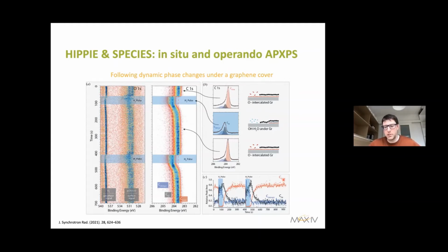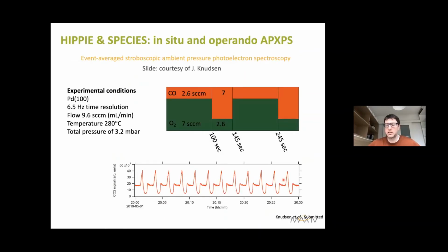In this particular case, the time resolution is on several tens of seconds. If you want to study faster processes, we need to slightly modify the method and choose a faster process. That was done in the next experiments, where a CO oxidation reaction on the transition metal palladium was studied. This oxidation is a pretty fast reaction, so a faster method, fast acquisition, was chosen. Previously we were using an acquisition of about 1 Hertz, 1 spectrum per second. In this case, on average 6.5 spectra per second were recorded, so the time resolution of this experiment was about 130 milliseconds.